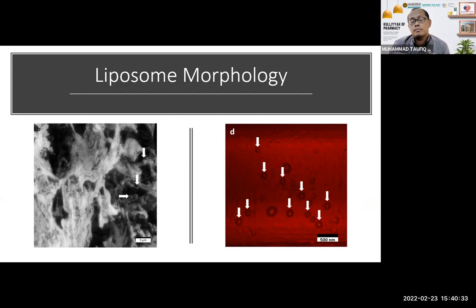So in this case, there are some problems in saying that, oh, this is the actual size. For example, you can see that there are some other bumps as well on the picture, but why didn't I select those? So the sampling becomes very selective, and it's just cherry picking between one another. So it's not really as quantitative as the Zetasizer with the hydrodynamic sizing. Even though hydrodynamic has its own limitation in that it assumes the particle is spherical. It's not necessarily spherical, but it assumes so based on the Stokes-Einstein equation.